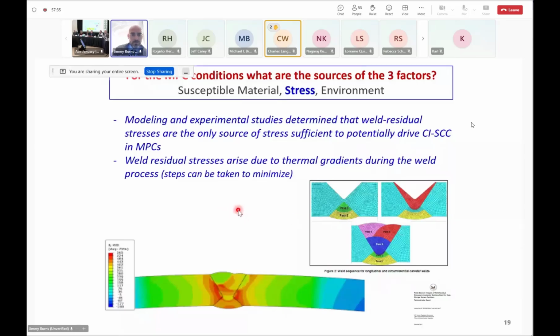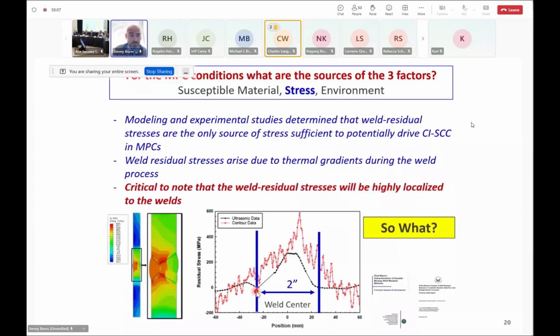Okay. Now, due to the thermal gradients, so welding is obviously hot, right? And then it's cooling down. During the thermal gradients that happen during the welding, you can get a residual stress profile just intrinsic to the material system. And so just sitting there, you can be under a stress due to this weld residual stress phenomenon. So there are steps you can take to minimize that. But it is a phenomenon that can happen.